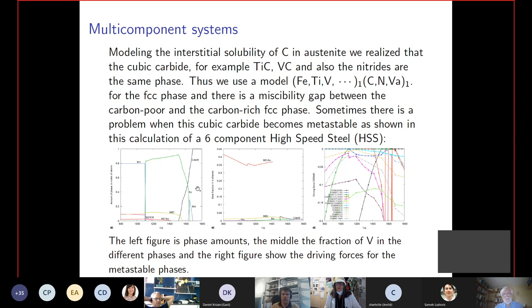This is the amount of phases. This is the composition of a specific phase. This is the cubic carbide, which is actually an FCC lattice, but you have mainly carbon in the second sublattice.